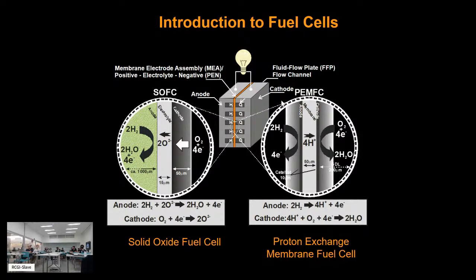Now, in a high temperature device, the concept's exactly the same. We're putting in a hydrogen rich gas. On the air side, we're putting in oxygen from air, usually again. But oxygen is accepting electrons from an external circuit, which now produces oxide ions. This material is an oxide ion conductor. Those ions will cross the membrane. Again, it's not an electron conductor, it's an ion conductor. Those oxide ions combine with the fuel to produce water, and so again we get a flow of current. The big difference is that now we're producing water on the anode side, whereas here we're producing water on the cathode side. So technologically, that matters quite a lot.